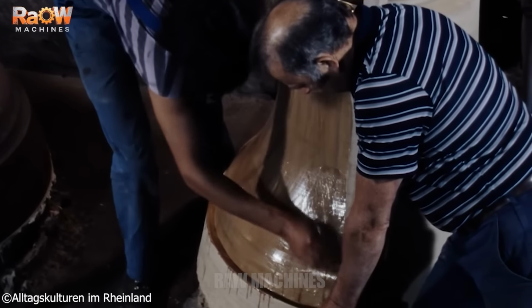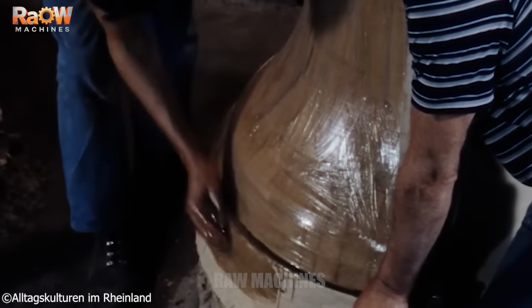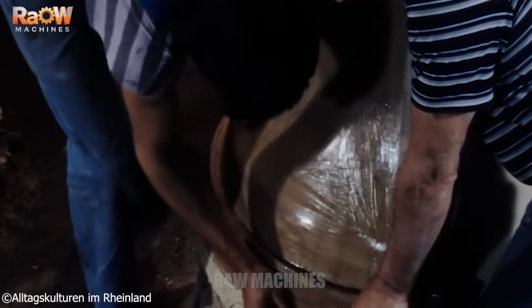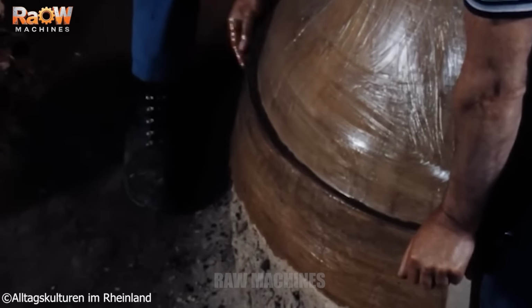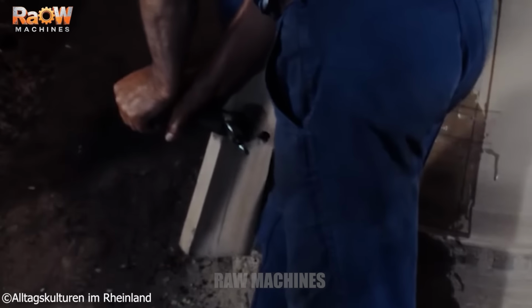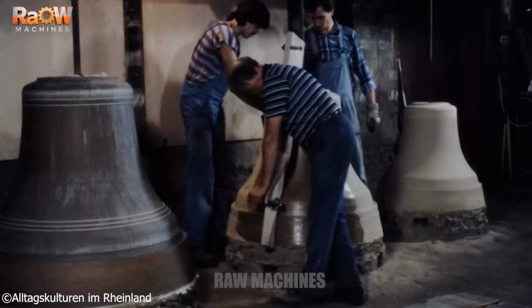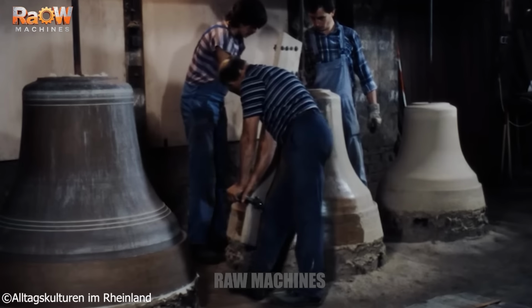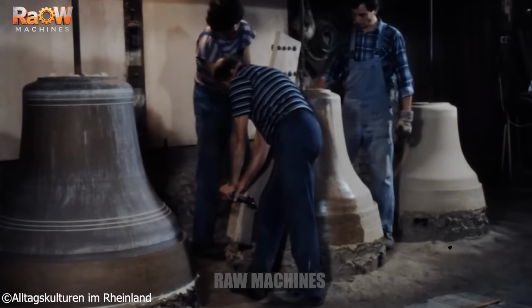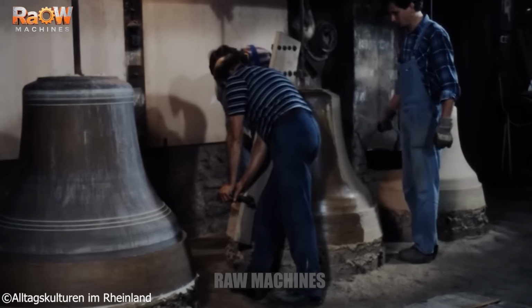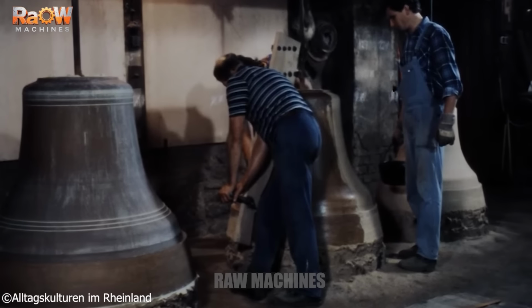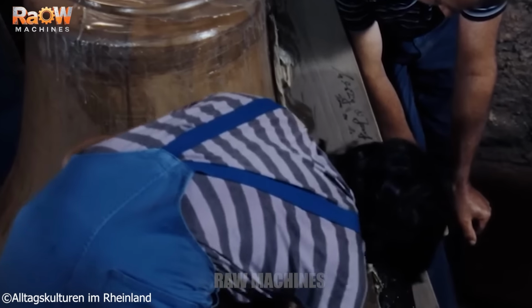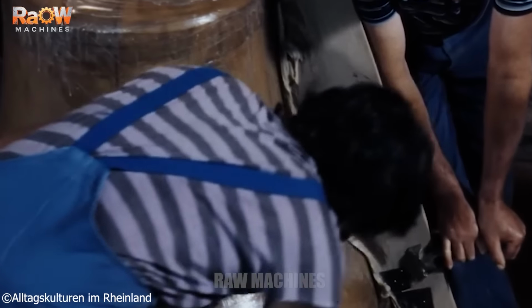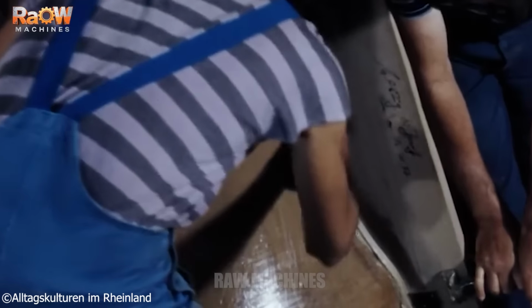The texts and decorative motifs are supplied by the commissioning parish, with each bell bearing its own inscription. The reference lines are transferred onto the schablone and notched into the wooden template to serve as positioning guides. The surface of the false bell is then coated with a very thin separating layer made from a mixture of beef tallow and lard, applied entirely by hand. The mixing ratio is adjusted according to workshop temperature to maintain a consistent viscosity.